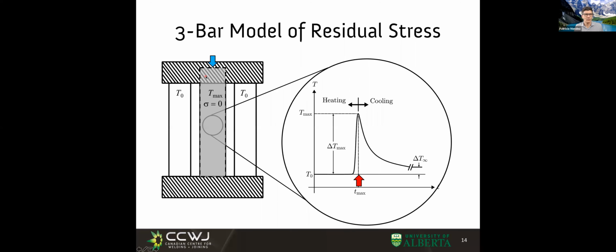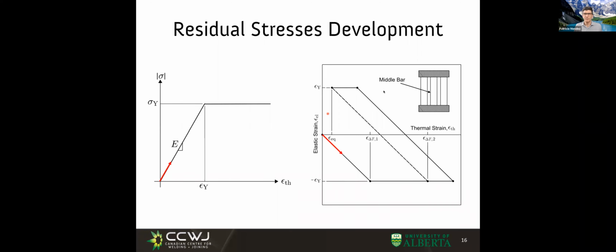It would be like if it wants to be bigger at no load, but in reality it's the same size, so it gets compressed, and depending on how much it wanted to expand, it can reach yield stress. It doesn't get much more than yield stress. But as it wants to expand more and more, with the same yield stress, it starts having more and more plastic deformation. So here are the curves I was asked about. At the beginning, the middle bar wants to stretch thermally, and if it stretches only a little bit, it stretches elastically.